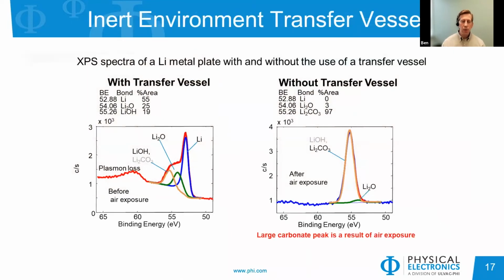And this just shows, with and without the transfer vessel, what you may expect to see. If you transferred a lithium foil just in air, it will quickly form a passivation layer of hydroxides and carbonates, and you wouldn't really see any sign of a lithium metal, for example. In this case, with the transfer vessel, this sample was sputter cleaned and then put in a transfer vessel from a glove box and moved in and out. And you can maintain some of the lithium, but you are seeing carbonates and hydroxides form fairly quickly, even when you do that.